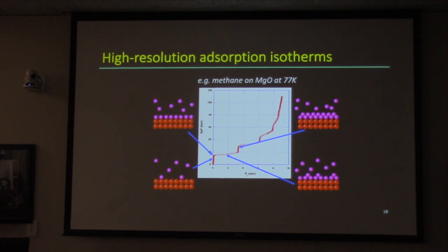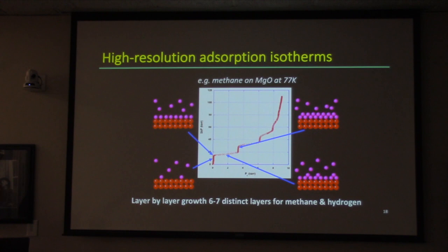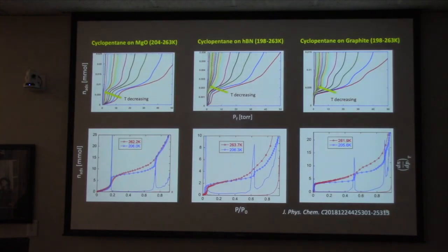What's cool that I've learned since then is these are solid layers, so what happens is you deposit the first layer, then you increase the chemical potential because this is at constant temperature. And if you take the logarithm of that pressure in your head, then it's basically mu, so there's the chemical potential. You need a higher chemical potential to condense the second layer. Needless to say, you need a little bit higher one for the third, etc. And there's some key systems that you can study that with. It turns out that it's the same thing for hydrogen. Hydrogen, actually, you can follow, in some cases, 7, 8, and 9 layers.